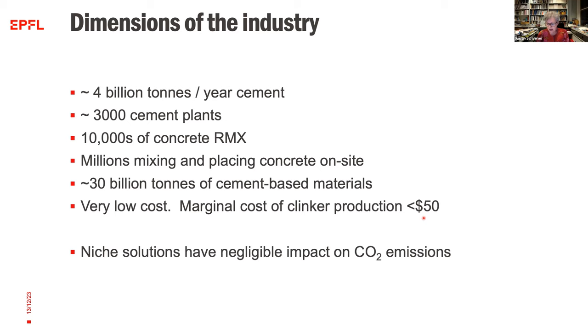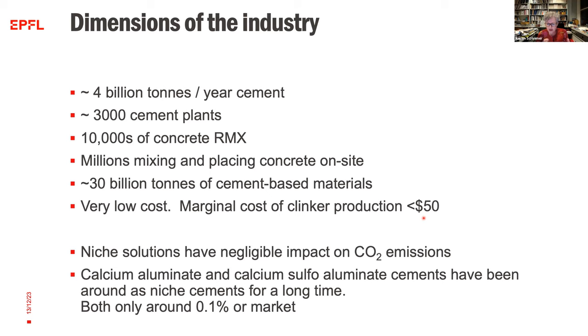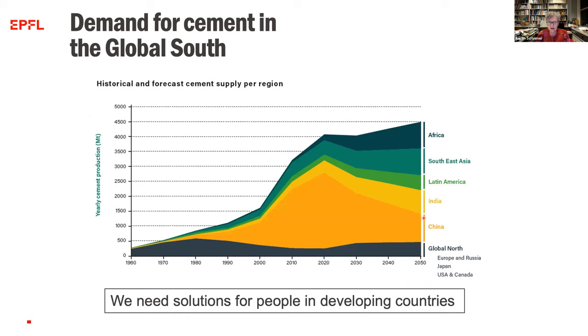And just to show you that alternatives really are niche, if we take the example of calcium aluminate and calcium sulfoaluminate cements, these have been around for a long time, many decades, but they're not more than about 1,000th, 0.1% of the market. So clearly, even if they were completely zero carbon, it would have virtually no impact on the overall emissions. And the other thing we have to bear in mind is where cement is being used.